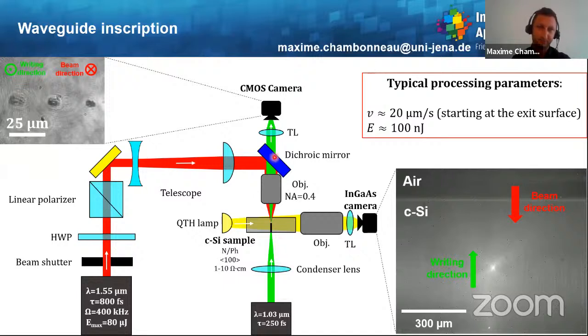which allows us to take images of the interaction and monitor the interaction in the XY plane, where Z is often called the optical axis. So here we are perpendicular to Z. Besides, we have another microscope relying on white light emission, an objective lens, and an infrared camera. So we can see through silicon and monitor the interaction in the XZ plane. You can see here a typical inscription where the bright part corresponds to the current laser focus.